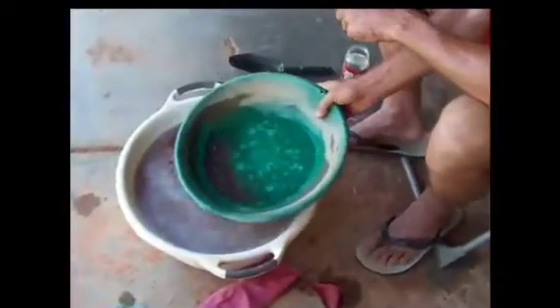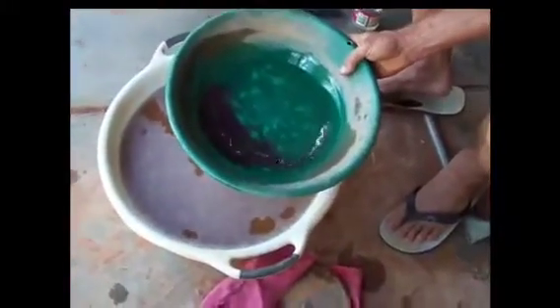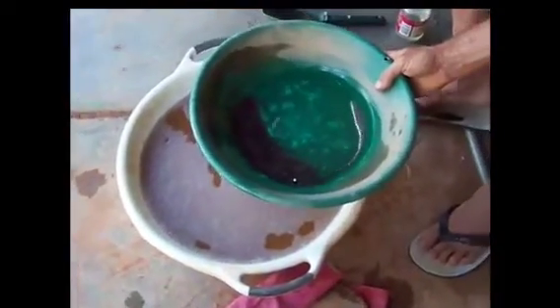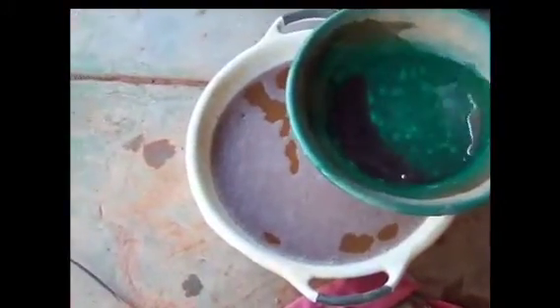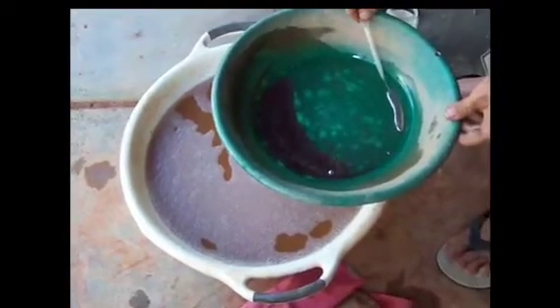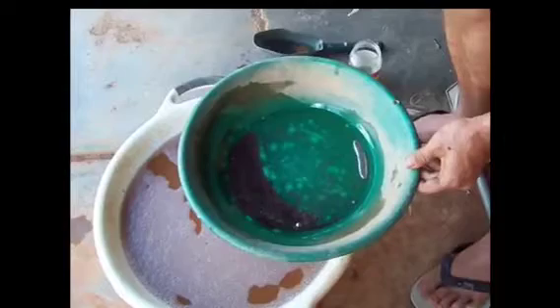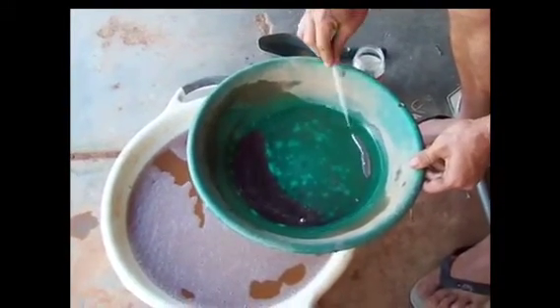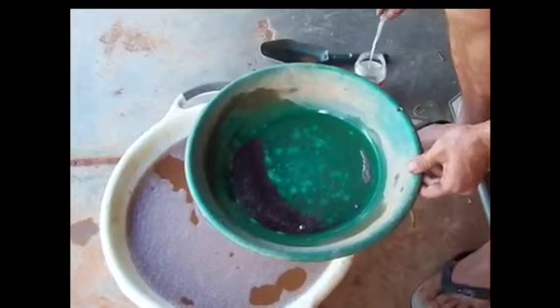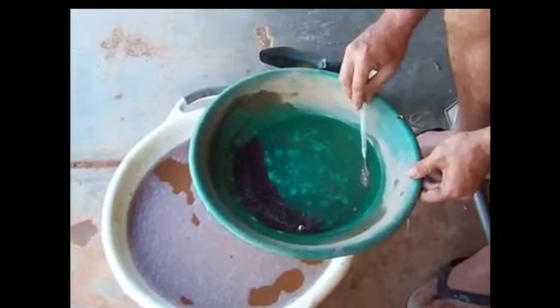Alright, so I've gotten the pan all down now — just like that. You can see I just roll it back and basically all the mercury rolls back down the pan. The stiffer bits will stay at the top — now they're a bit stiffer because they're loaded with gold. So what we do is just suck all this stuff up with a pipette, so it's not touching none of it. It's going solid into an amalgam almost straight away — there's a hell of a lot of gold in this lot, that's why it's going so solid like that straight away.